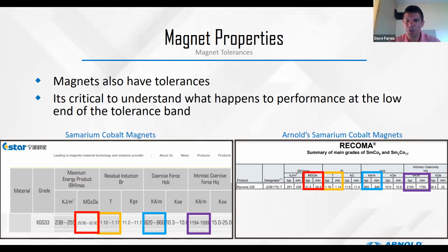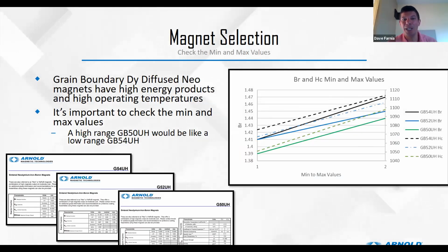The magnet manufacturers will always talk about the intrinsic coercivity. So that really determines how far you can push the magnet out at temperature. So a higher intrinsic coercivity is going to result in better temperature resistance, so less permanent magnet property loss with temperature due to that higher intrinsic coercivity. And again, this is where we really get into that difference. So it's critical to understand what happens to performance at the low end of the tolerance band. This goes for the neomagnets as well.